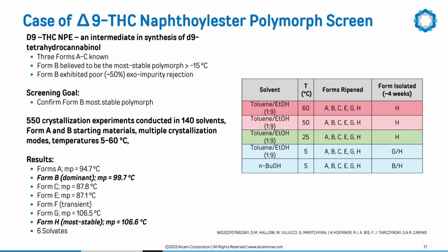Competitive ripening of all non-solvated forms A, B, C, E, G, H, conducted at various temperatures, confirmed that between 25 and 60 degrees Celsius, form H is the thermodynamically stable form. At 5 degrees C, experiments were incomplete within a month. However, they also suggested that form H is more stable. Therefore, it was recommended that form H is the progressed form for development. Therefore, the program needed a form switch. This led to the redesign of the current crystallization process.